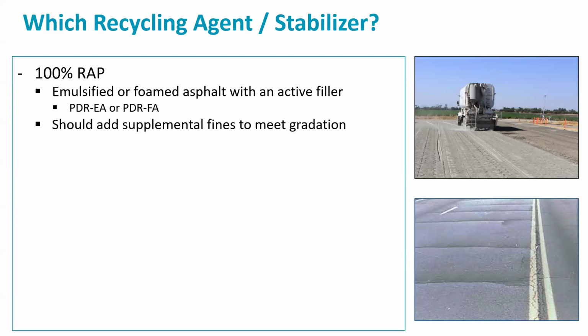Certainly in terms of the Caltrans specifications, they leave it up to the contractor to decide what recycling agent they want to use, but they're both good. We also try and encourage adding some fines. 100% RAP tends to be a little coarse, so just a low percentage of some finer material to help with the active filler cement that we add down there, just to get a good tight gradation.